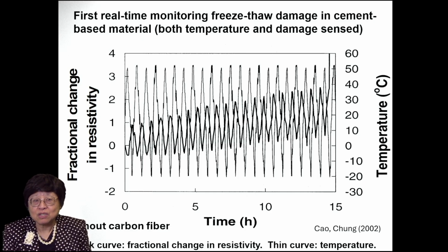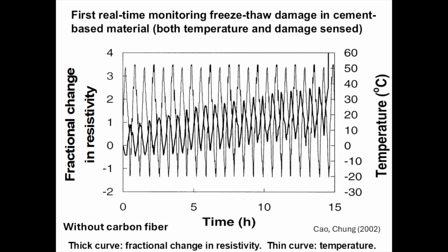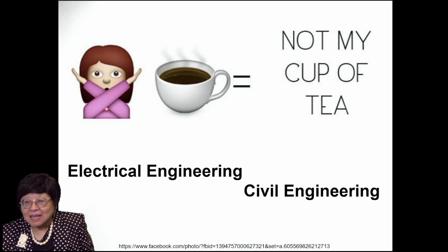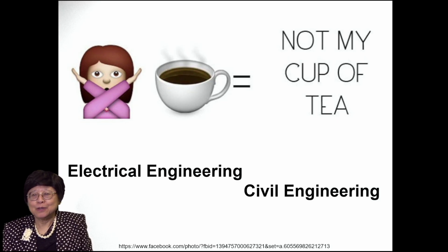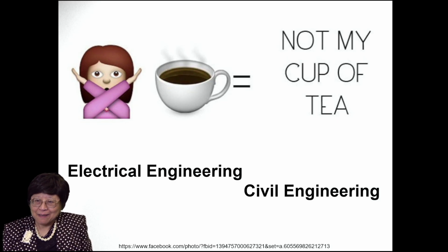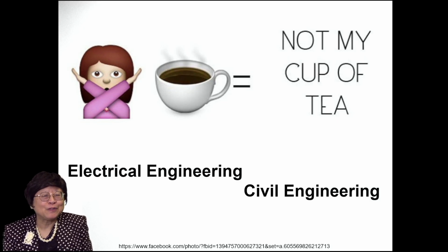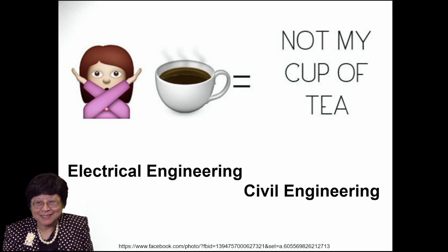But in addition, you see the upper envelope and the lower envelope increase as freeze-thaw continues. And that is because there's minor incremental damage inflicted in every freeze-thaw cycle. And just at the end, when it dies, the resistance goes up to like infinity, and that occurs at the coldest point of the last cycle. This is the first real-time monitoring of freeze-thaw damage in cement-based materials. And I found it very fruitful to marry electrical engineering and civil engineering. Very few people join these two fields together, but I find this to be just my cup of tea.